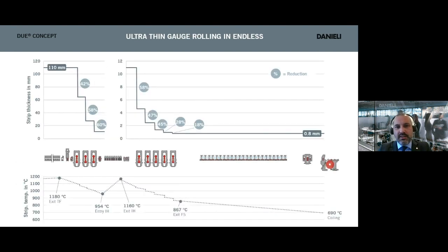With the Danieli Universal Endless, you can see now a schematic view of the possible reductions on the rolling mill stands, starting from a 110 millimeter slab, going down to 0.8 millimeters on the final strip. And in the bottom part, you see the temperature pattern along the line, which of course calls for an intermediate reheating, which is made through an induction heating system.